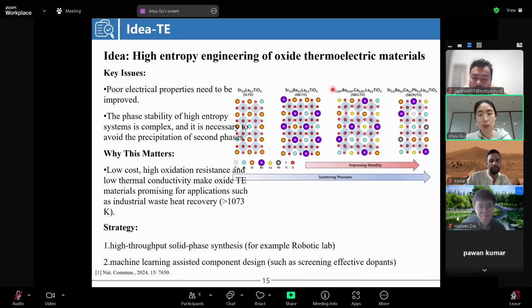And this is a paper published in Nature Communications in 2024. It is about perovskite thermoelectric materials. They use high entropy engineering as well, but they grow films to perform the experiments. So I think we can use bulk to perform the high entropy engineering on the oxide thermoelectric materials. I think it is promising.